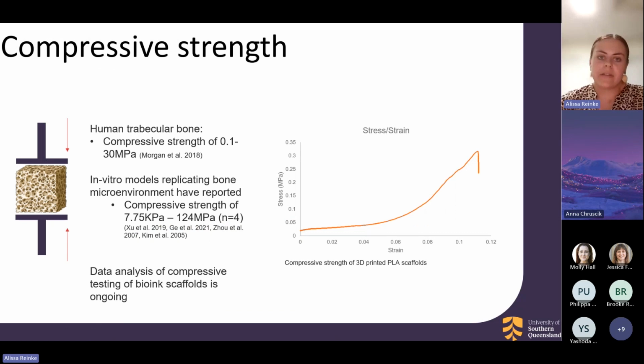Obviously, I've spoken about the strength of the scaffold, so this is something that we are also testing. Human trabecular bone has been reported to have a strength anywhere from 0.1 to 30 MPa. And of the papers which are trying to create an in vitro model replicating the bone microenvironment, they have reported compressive strength of their scaffolds from about 7.75 kPa to 124 MPa.